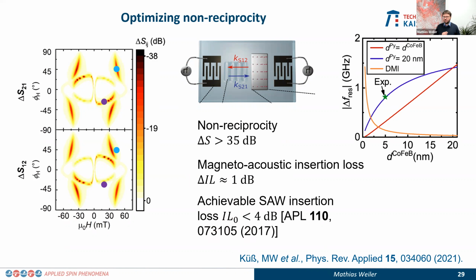That's exactly the insertion loss you get with a surface acoustic wave filter in your mobile phone, which in the best commercially available ones is apparently about 2 dB, while some found in the scientific publication at the frequency that we operate can be about 4 dB. Okay? And of course, there are further possibilities to optimize this non-reciprocity, for instance by changing the thicknesses of these individual layers.